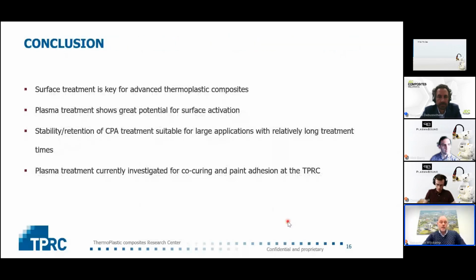So surface treatment is key for the advanced thermoplastic composites. We see great potential in plasma treatment for surface activation, and specifically the stability of the CPA treatment seems suitable when you have to spend longer times treating a part before it's bonded or, for example, painted. So that's good. And we are currently continuing our plasma treatment for co-curing and paint adhesion, and really trying to understand, getting up to the level of understanding as Plasmabound of the mechanisms that play a role with the specific materials that we research.